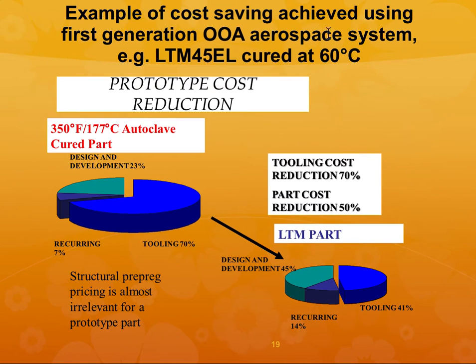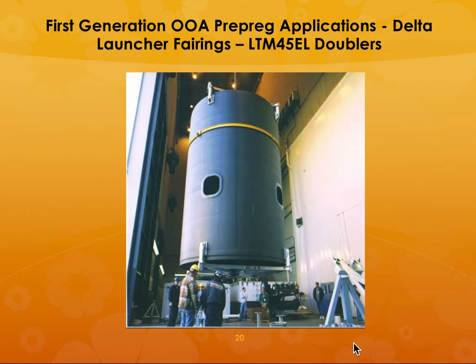So here is an example of cost savings achieved using the first generation, which is low temperature curing at 60 degrees centigrade. They have figured out that you're saving 70% of the cost in the tooling, and design and development is 23%. So it gets down to this much. Almost, tooling cost reduction is 70% and part cost reduction is 50% using this approach. So this is the Delta launcher fairings, and they are made using low temperature out of autoclave pre-preg.